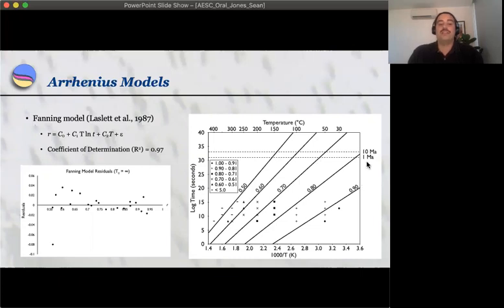From analyzing these contours, we can then constrain the temperature range in which the fission tracks partially anneal over geological time, known as the partial annealing zone. In this study, we've defined the lower temperature limit of the monazite partial annealing zone as with a track length ratio of 0.95, since a track length reduction at the 5% level should be clearly detectable under the microscope.